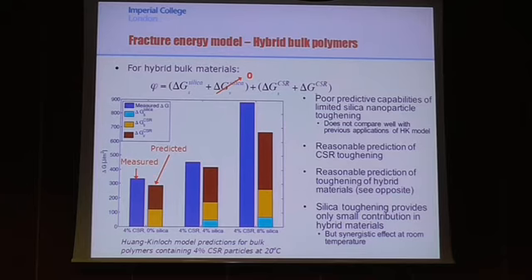So I have an example here of our measured and our predicted. So we have reasonably good prediction when we go from 4% CSR and adding in the hybrid materials, 4% silica and 8% silica. And what we see actually is that the presence of the silica, while it doesn't add a whole lot to the actual toughness, what it does is enhance the ability of the CSR voids to grow. So what the actual presence of the silica is doing is providing a synergistic response. It's allowing the voids generated by the cavitated CSR particles to grow much better.